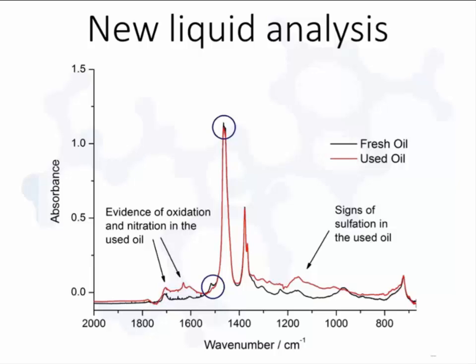But if you take that oil and put it in a motor for 18 months, then you would expect it to be chemically degraded slightly. And that's what the red spectrum is. It's just a bit of used oil. And I've compared the two, and you can see that for the most part, the spectra look the same, but there are some new features that weren't previously there. So around 1200, we see signs of sulfation, and around 1600, there's evidence of oxidation and even nitration in the oil. And that's just a clear indication that the oil has been changed chemically.